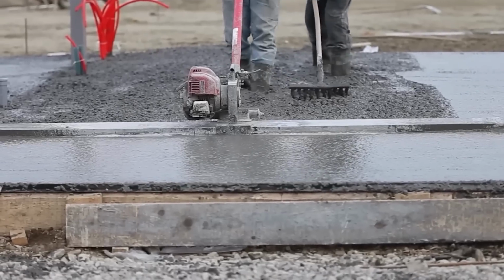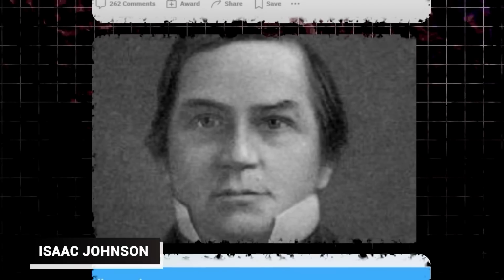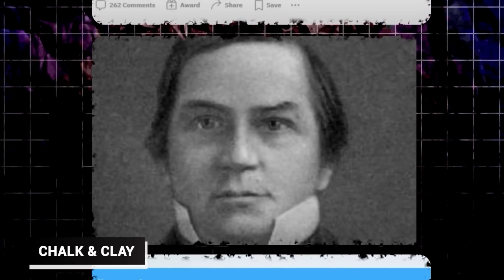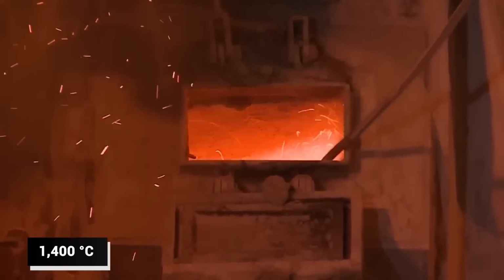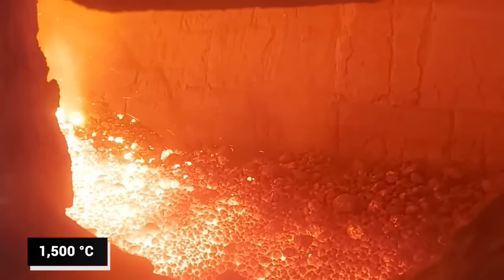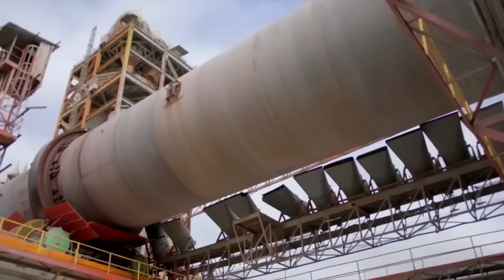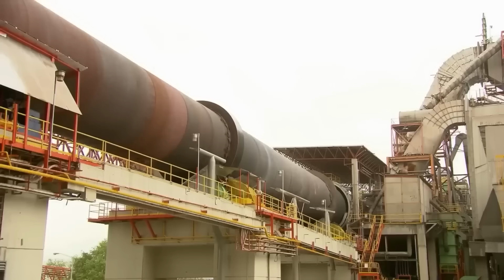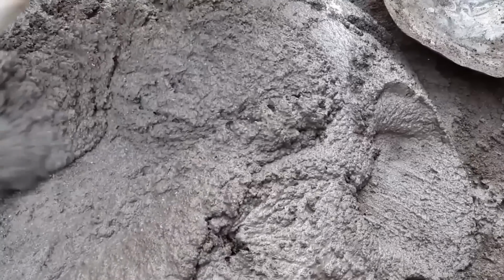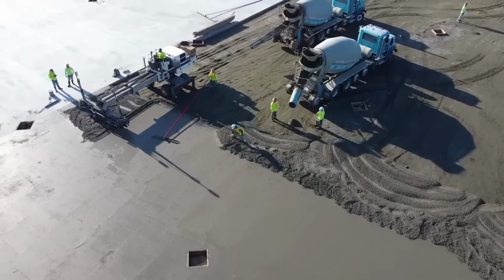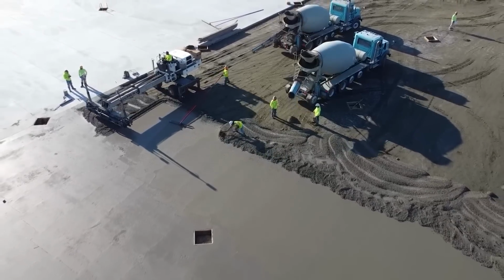That milestone was reached in 1845 when Isaac Johnson fired a mixture of chalk and clay at much higher temperatures, between 1,400 degrees Celsius and 1,500 degrees Celsius. This process, known as clinkering, produced minerals that were highly reactive and provided the cement with much stronger binding properties, paving the way for the cement we use in modern construction.